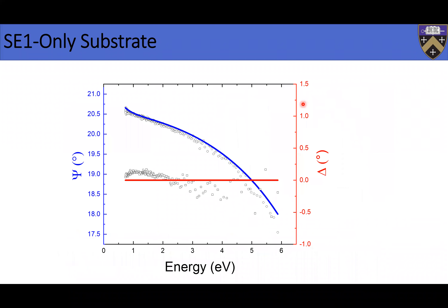The first step is the substrate — SE1, only the sapphire. We've measured psi and delta as a function of energy using the in-situ ellipsometer coupled to the MBE chamber. The symbols are the experimental data. In the ellipsometer software, there's a library of optical constants for various materials and substrates. Sapphire's dielectric function is well known, so we take that from the library, model and fit the data, and get a pretty good fit. The scale fluctuation is only about half a degree — very small.